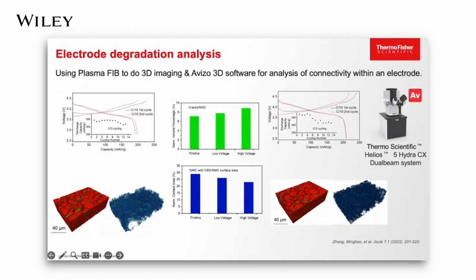The images collected through PFIB, plasma focused ion beam, are reconstructed to create a 3D model of the electrode with Avizo 3D software, and then the cracks and connectivity between NMC and carbon binder domain, here named CBD, are quantified through the 3D volume. Then you can compare the impact of this structural information as shown here. The electrode for the higher voltage cell experienced heavier cracks and disconnections inside the electrode. In summary, PFIB technology combined with the software provides a powerful tool for acquiring large, detailed 3D images and understanding the structural and chemical complexities that drive battery degradation.